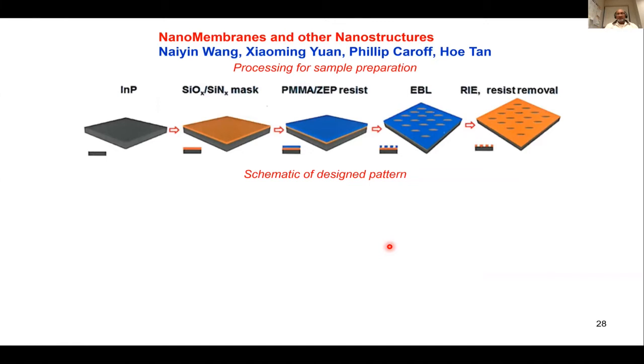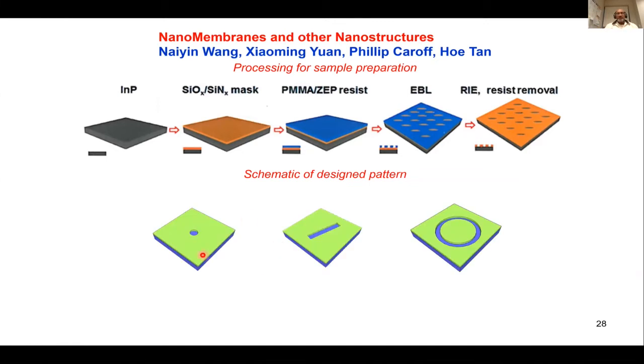So we asked ourselves, instead of opening a hole in this mask, what will happen if you open a slot or a ring? What interesting structures can we grow? This is the work of my student, Dr. Naiyin Wang. He spent about 4 years taking an indium phosphide substrate, putting on a silicon dioxide mask and photoresist, doing electron beam lithography to create a hole, a slot or a ring, and then trying to grow these nanostructures to see what structures we can get.